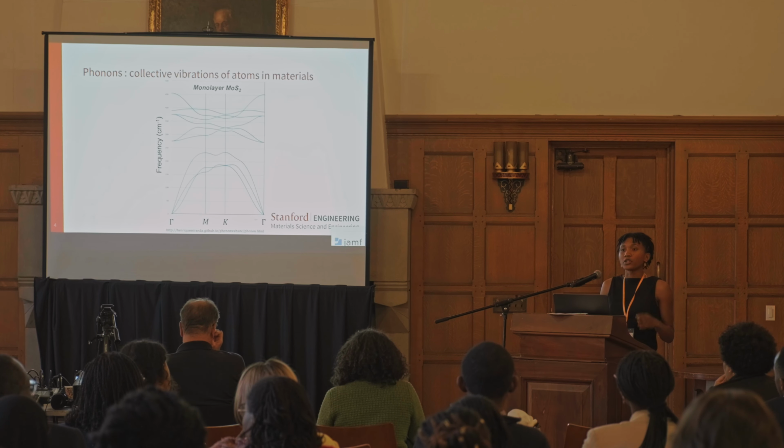In the Liu lab, we use the technique of gold tape exfoliation, where we take advantage of the strong adhesion between a metal, here gold, and a monolayer to break the van der Waals forces of the material and, layer by layer, disassemble the bulk crystal into individual monolayers.